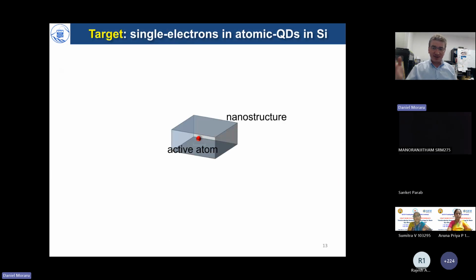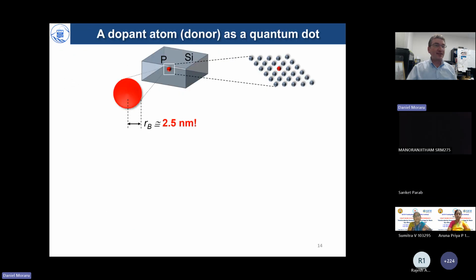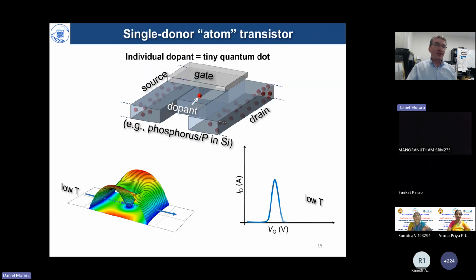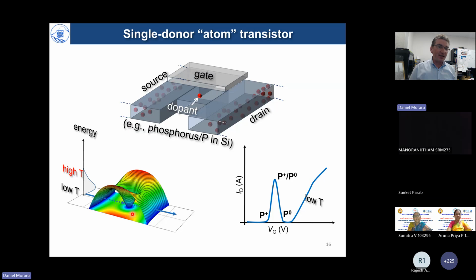So the main issue is that it actually disturbs the lattice of a silicon. So we assume that doping occurs very naturally as substitutional doping. But when we do ultra-high doping concentration, interstitials will also play a significant role in the doping. And those interstitials create stress, strain, and they may modify the properties of silicon itself significantly. So we have to deal with concentrations that are sufficient for us to create quantum dots without disturbing the lattice of the silicon too much. So this is maybe the most important challenge.